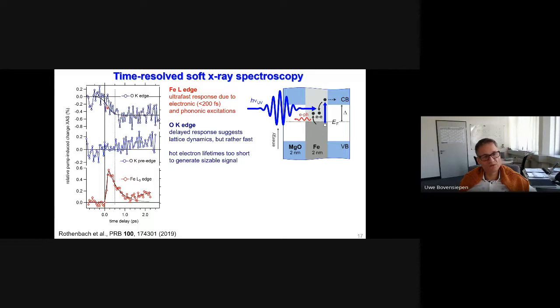Now, what do we see at the oxygen K edge? And this is obviously a difficult experiment. We have a lot of noise here, but you can clearly see that there is a delayed response with respect to iron. So this means that this injection from iron into the conduction band of MgO is not a process that we observe. We rather observe this electron-electron scattering and electron-phonon scattering. Now, the response of the oxygen K edge is faster than this response which we see due to electron-phonon coupling in iron, but the time scale suggests that we indeed have some phononic dynamics here. The pre-edge dynamics I will discuss in a moment.